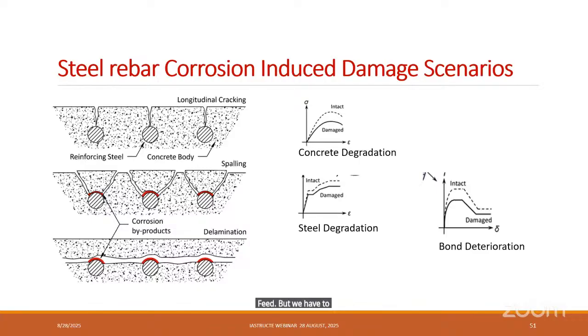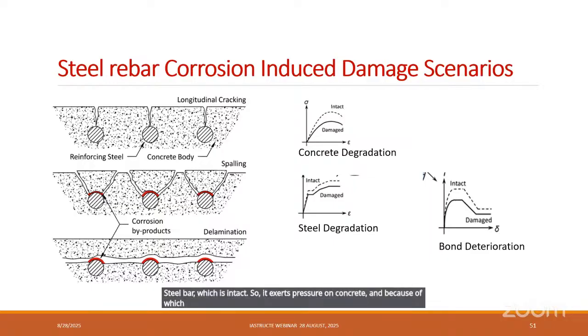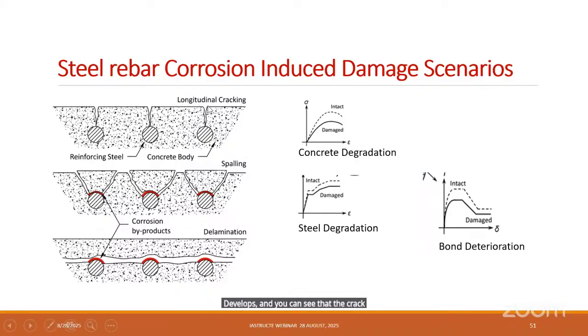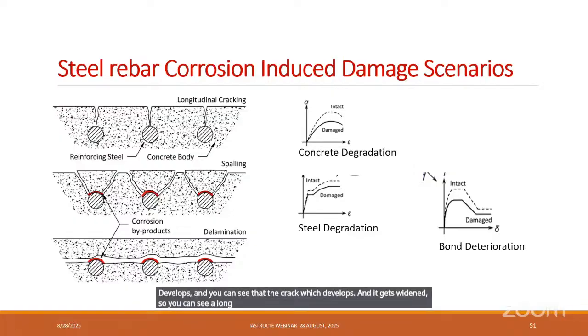But we have to understand that the steel, that is the reinforcement steel which is embedded in concrete, gets corroded, as I explained earlier, because of either carbonation or chloride attack. So you can see that first some cracks are developed, because the rust which forms has more than 8 times the volume of the steel bar which is intact. So it exerts pressure on concrete, because of which the cracking develops, and you can see that the crack which develops gets widened. So you can see a longitudinal crack along the length of the rebar when you inspect the bridge.